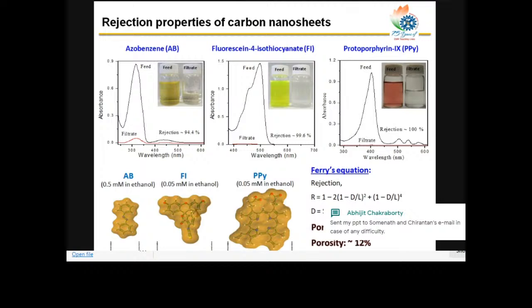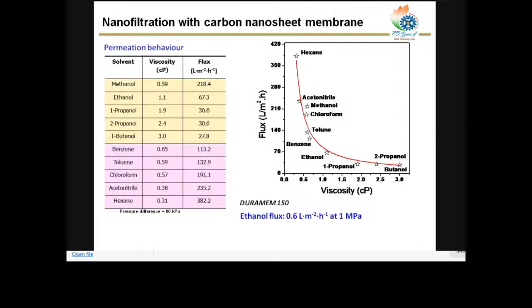But if you increase the size to a certain extent, like fluorescein 4 isothiocyanate, you can see almost 99.6%. That means we can achieve almost complete rejection. That means the pore size is smaller than the size of the fluorescein 4 isothiocyanate. Eventually, if we took a bit bigger molecule, like protoporphyrin 9, we can get 100% rejection. In this case, you can see the filtrate is transparent. So there is no protoporphyrin molecule coming through the membrane. So from the rejection property of the membrane, we can calculate that the pore size is 0.7 to 1 nanometer, with a porosity, which means the number of pores on the surface of the membrane, of about 12%.